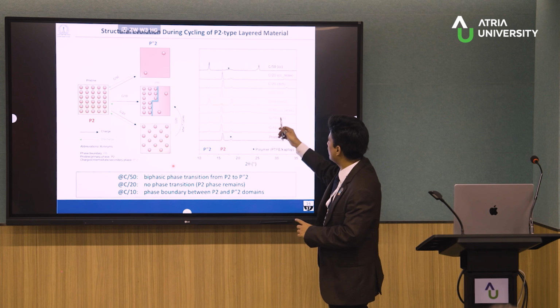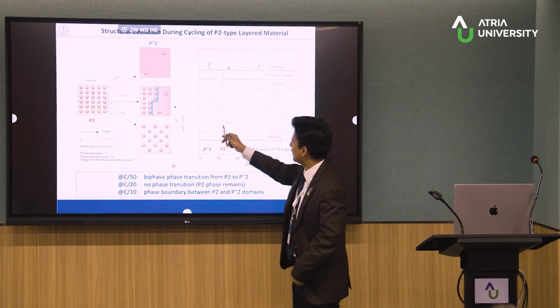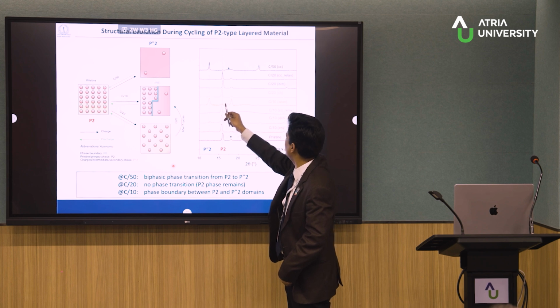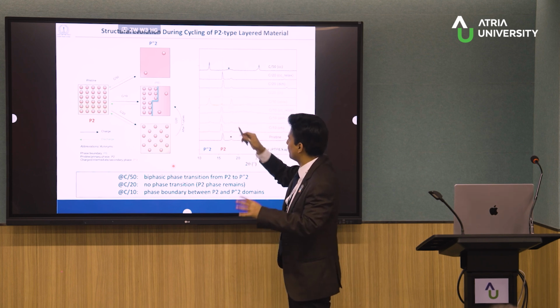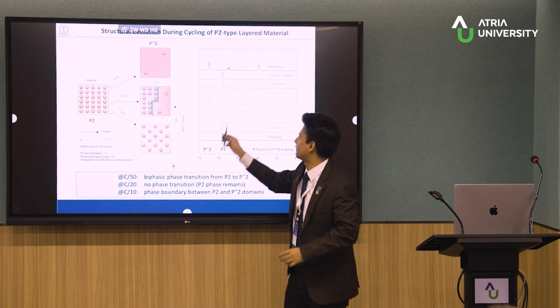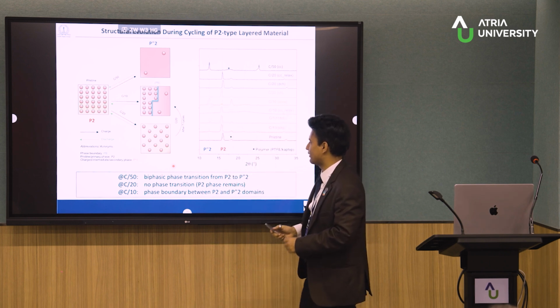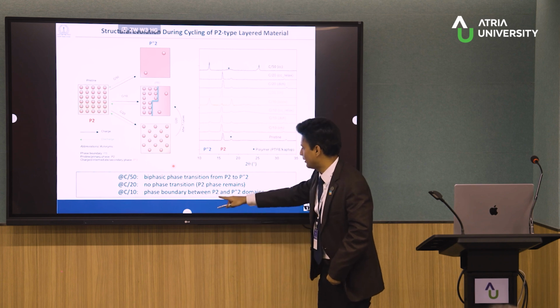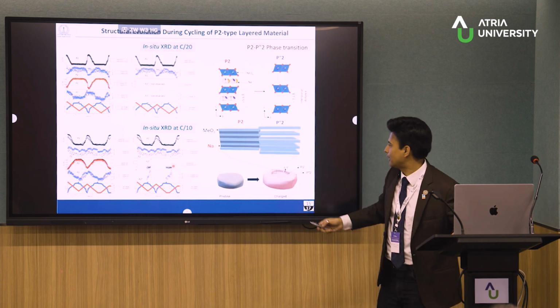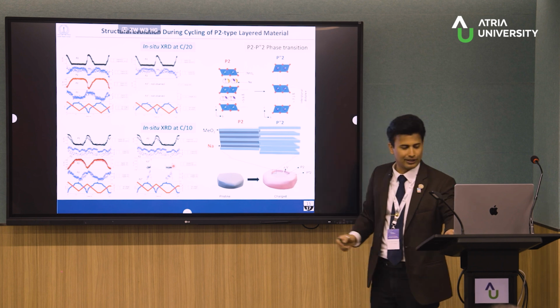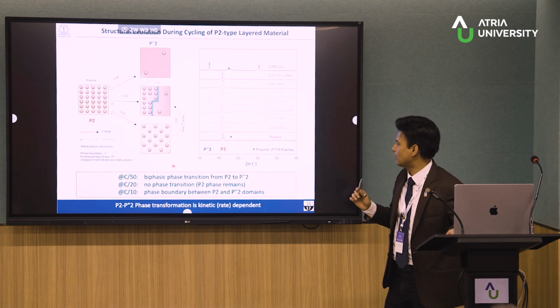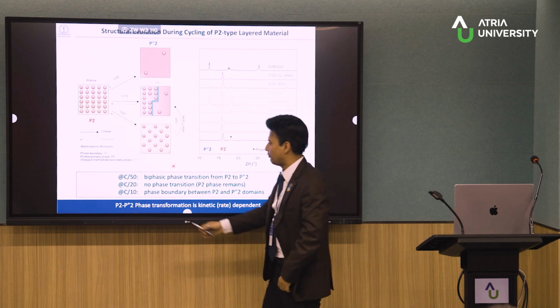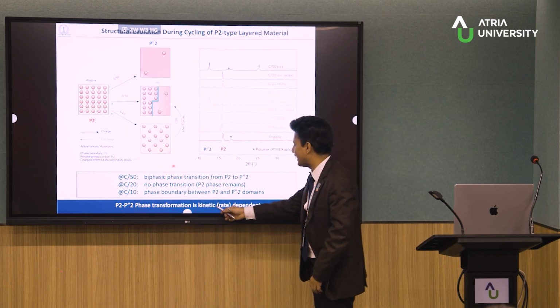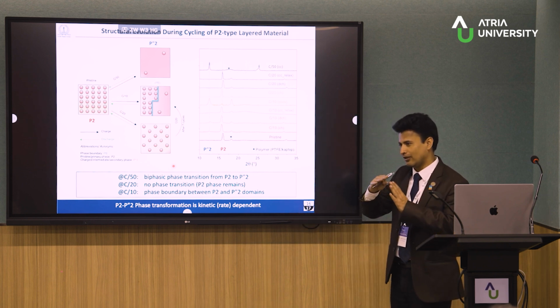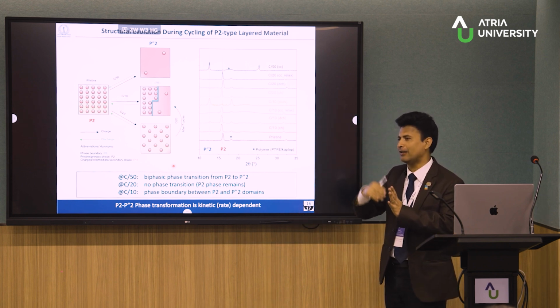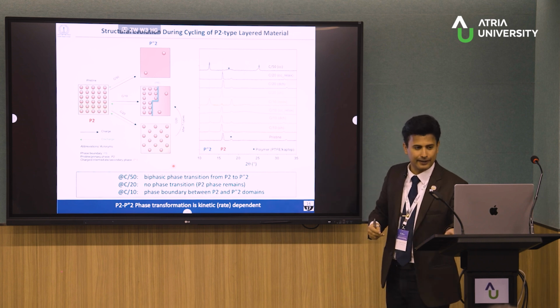Initially if I just do the charge discharge, we are getting some amount of P'2, and if I go to high voltage and do CCCV, keep it for a long time, slowly everything will become P'2. One is decreasing, the other increasing. So here we have a coexistence of P2 and P'2 domains, as was shown here. With this, I want to conclude that we found the P2 to P'2 phase transition is kinetic or rate dependent. So it is not only that the phase is changing, it also matters the degree of phase change, how fast or slow you are charging.